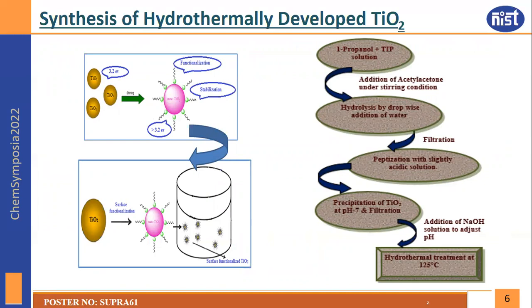This is the flow chart for the development of the hydrothermally developed TiO2. For this development, first of all, titanium isopropoxide was taken in the solvent 1-propanol. It was functionalized with the very well-known functionalizing or stabilizing agent, acetyl acetone, and it was hydrolyzed by dropwise addition of water. The obtained precipitate was filtered and it was peptized with the addition of a sufficient amount of nitric acid.